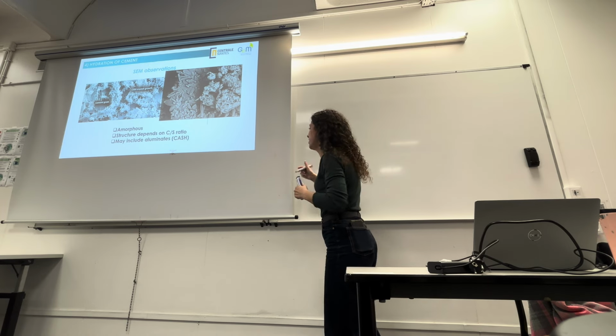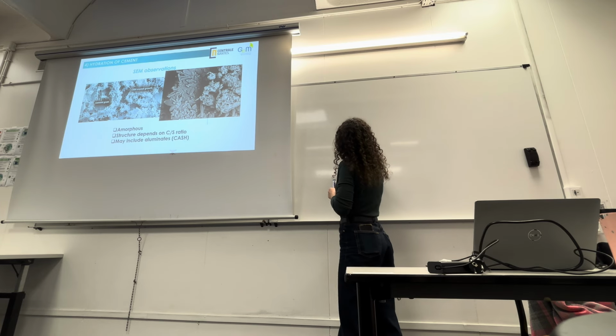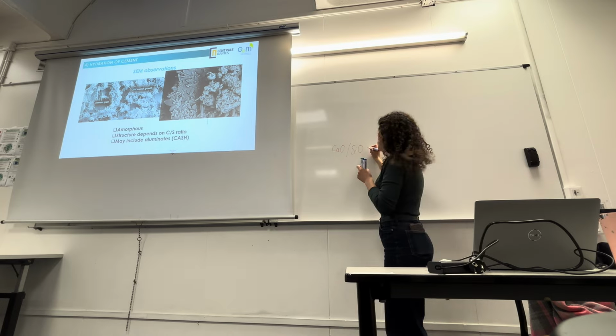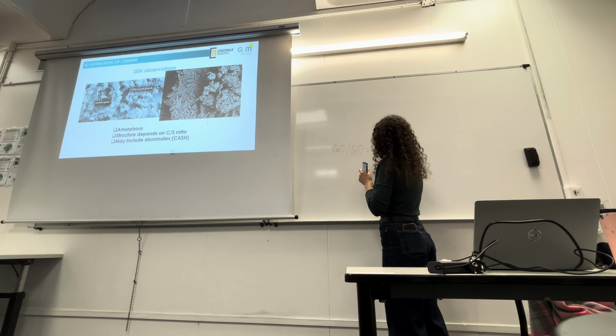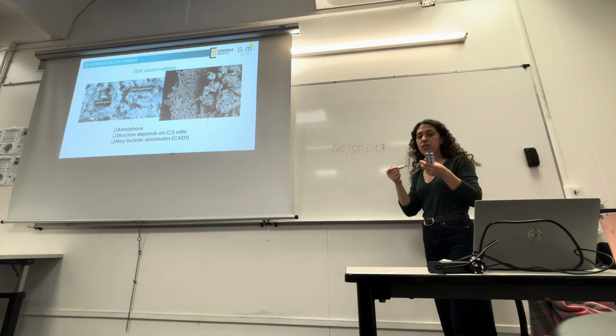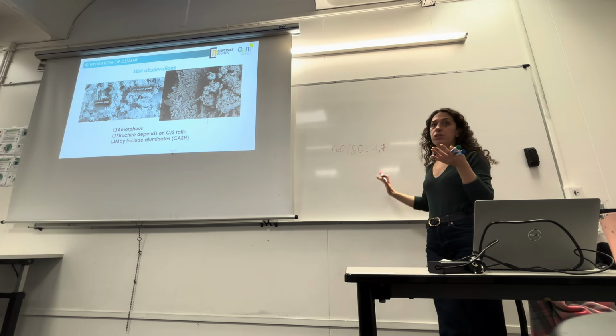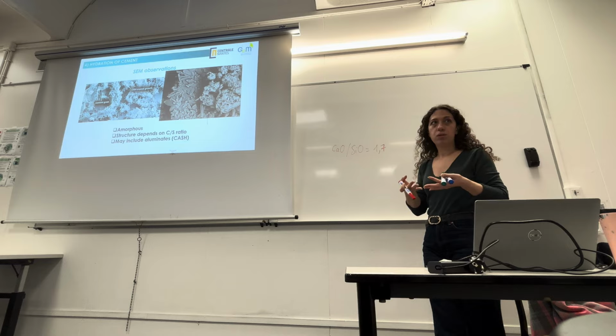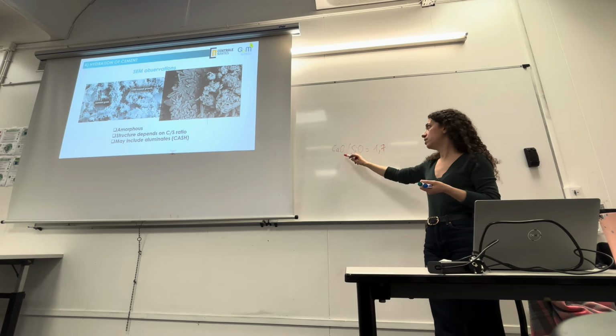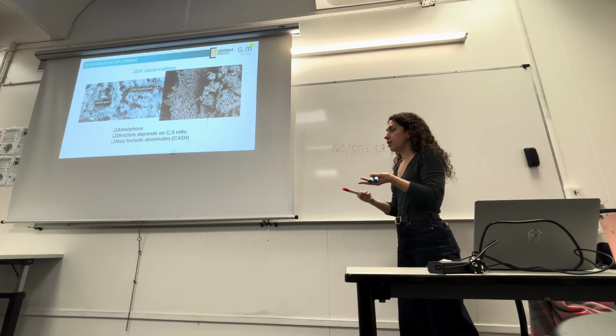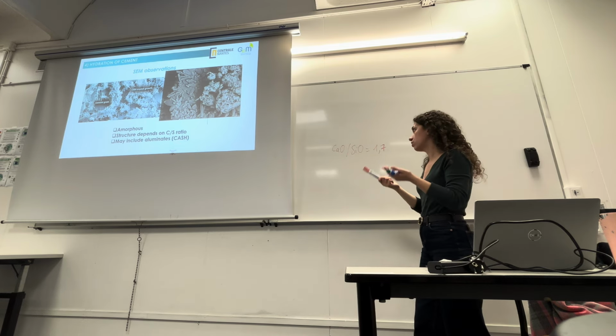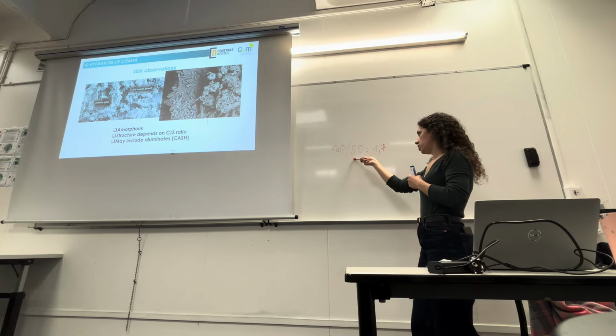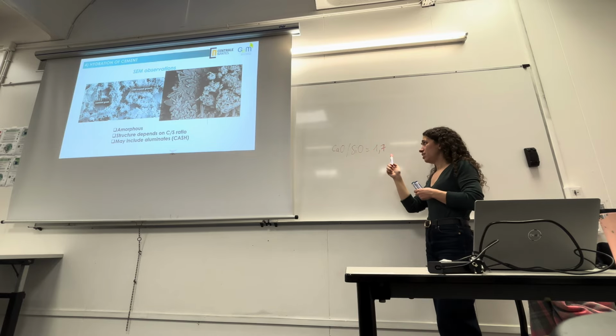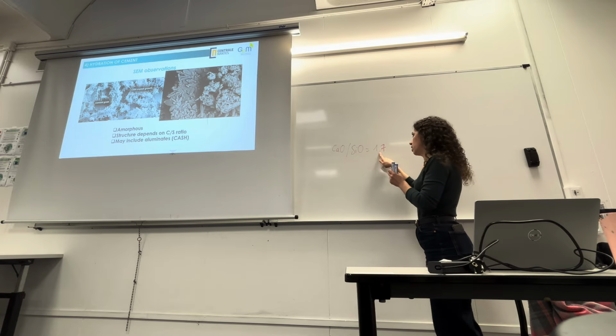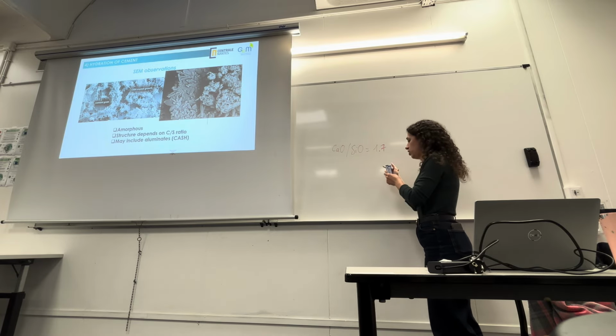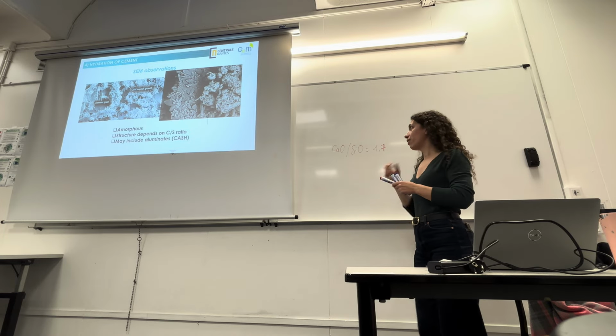And it's very important. So, calcium silicon ratio. For the CSH in cement, it's around, once again, we cannot determine this ratio precisely because cement is a specific environment with specific conditions, and CSH is not the only hydrate we have in the environment. But the calcium silicon ratio of CSH from cement paste is, we're talking 1.7. Okay.